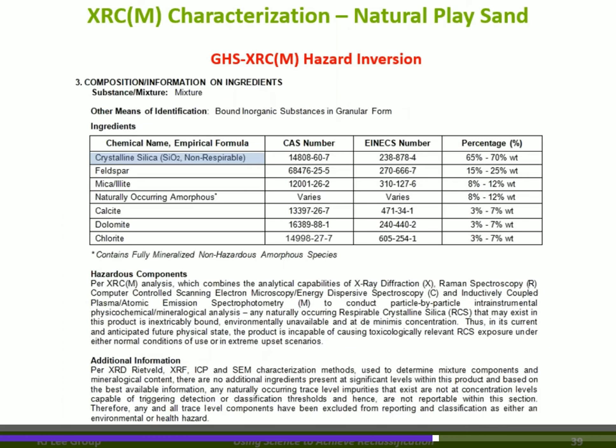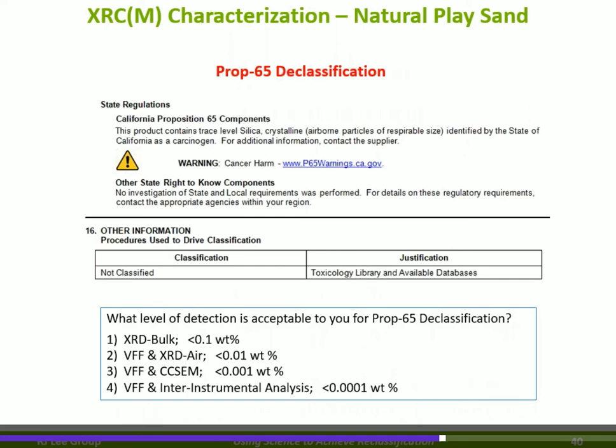We do not classify. And what we do to support that is we advise this safety data sheet information that the crystalline silica SiO2, non-respirable, be what's reported, 68%, and that you add the language: we've gone through this with XRCM analysis, and this product is incapable of causing toxicologically relevant RCS exposure under normal conditions of use or in extreme upset scenarios. Additional information just says that we've gone through this material in extreme detail in characterizing it, and we know that there isn't anything else in it that's going to cause harm either.